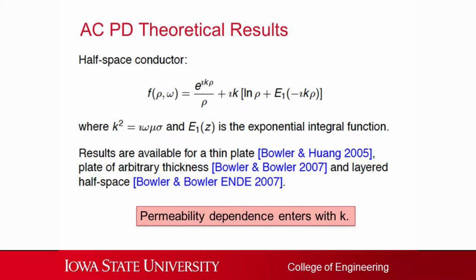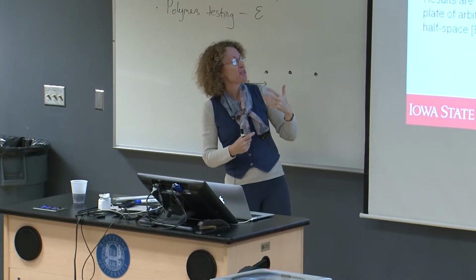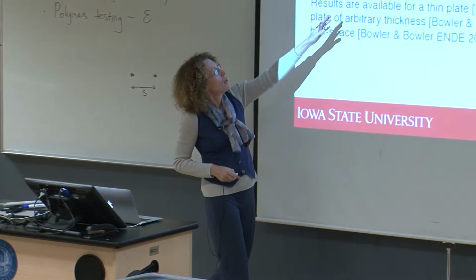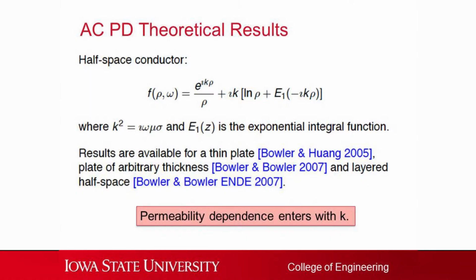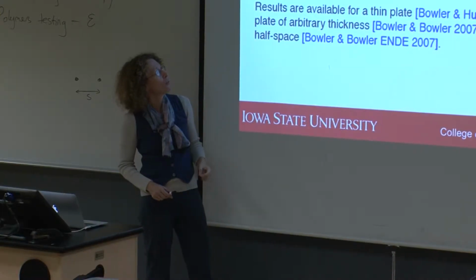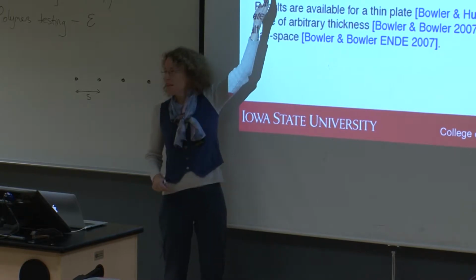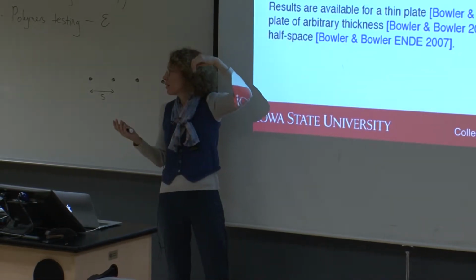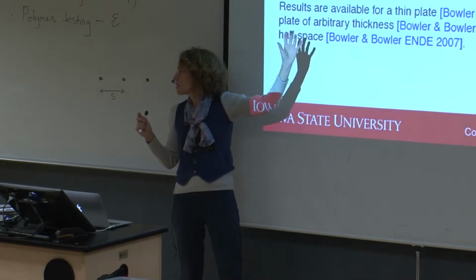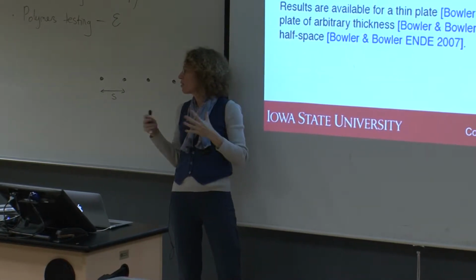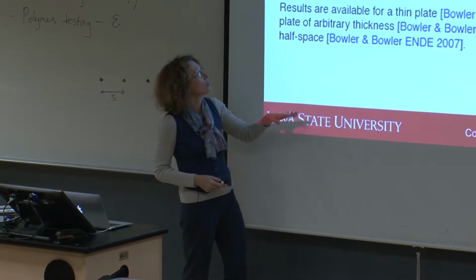If you take it up to higher frequency, though, you get a much more complicated formula for the dependence of that potential drop. So you have to go through lots of Maxwell equation type analysis to get this kind of equation here. And what's new is that we have this factor K in particular that is related to several things about the material and to the frequency. It's a kind of loss factor really. We're used to using K for a wave number. This is like the complex lossy part of that, because the metal is essentially a lossy conductor.